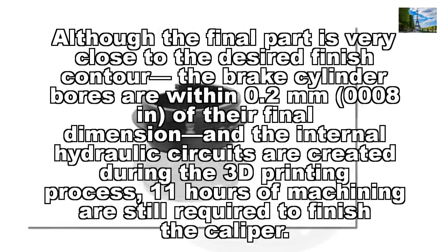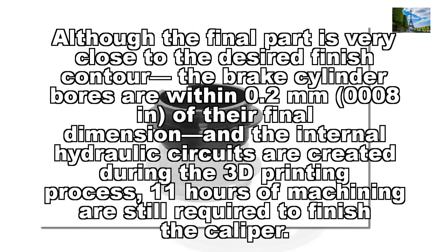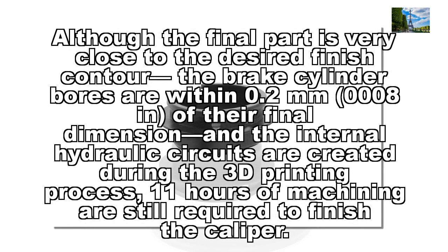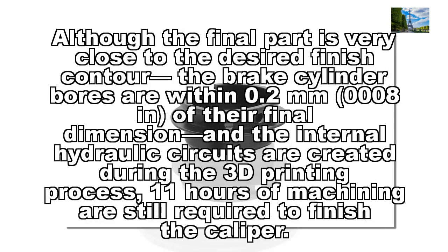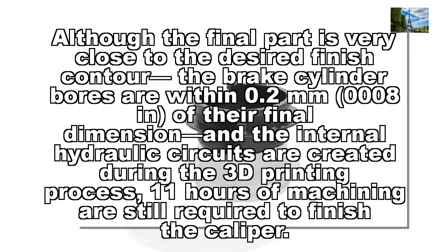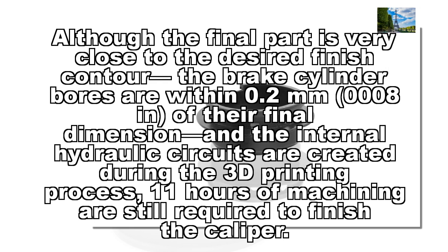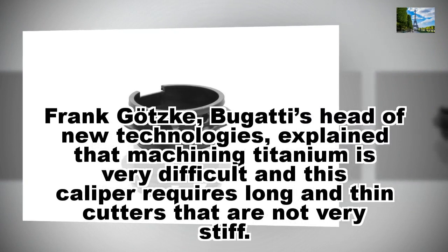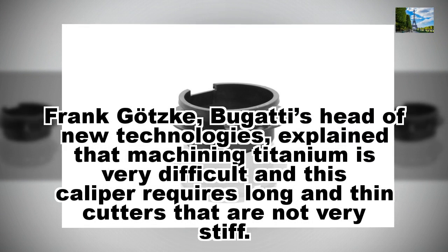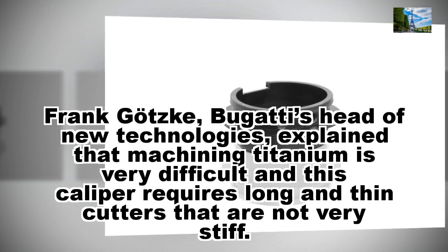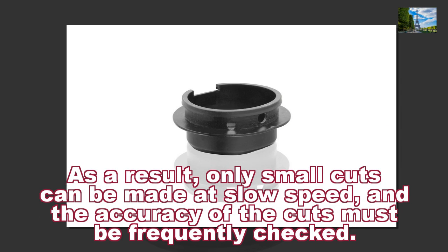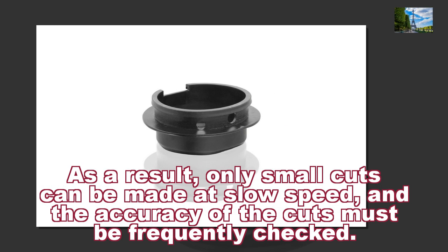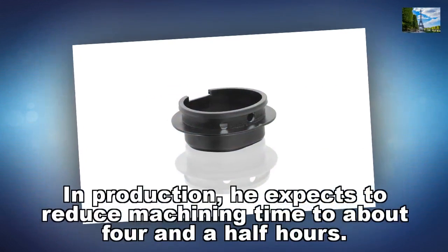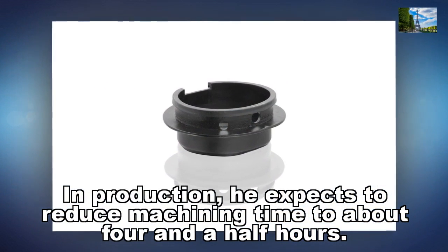Although the final part is very close to the desired finish contour, the brake cylinder bores are within 0.2 mm (0.008 in) of their final dimension, and the internal hydraulic circuits are created during the 3D printing process. 11 hours of machining are still required to finish the caliper. Frank Götzke, Bugatti's head of new technologies, explained that machining titanium is very difficult and this caliper requires long and thin cutters that are not very stiff. As a result, only small cuts can be made at slow speed, and the accuracy of the cuts must be frequently checked. In production, he expects to reduce machining time to about 4.5 hours.